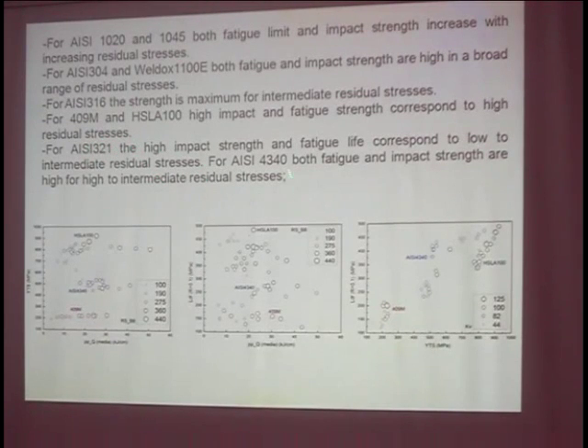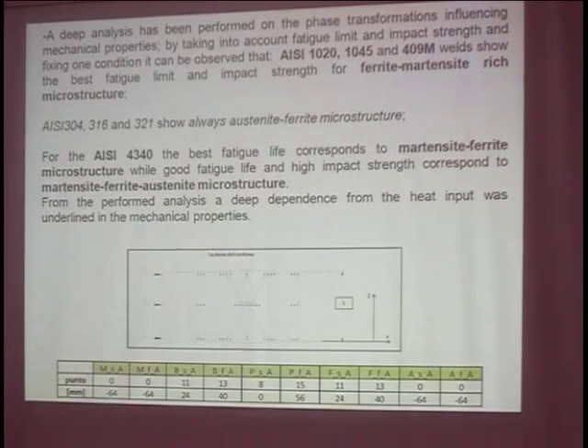And for AISI 321, the impact strength and fatigue life are in correspondence of intermediate residual stresses, while for 4340, both fatigue and impact strength are high for high to intermediate residual stresses. And finally, we tried to correlate the mechanical properties, going back to the input parameters, optimizing the input parameters, having as a consequence the optimization of mechanical properties by taking into account the microstructural evolution, because the microstructural evolution of such steel welds is strongly influenced by the situation in the microstructure.